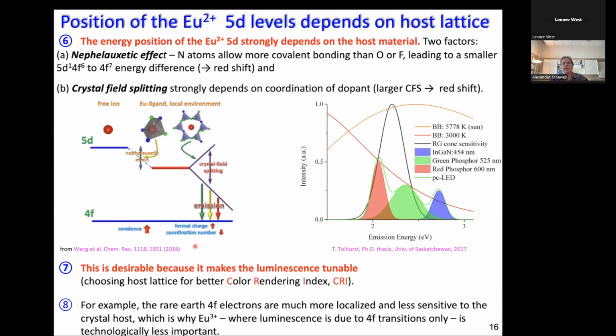Okay, now the whole point about 5D levels is, unlike the 4F, which are very localized, where it basically does not matter in which host matrix you put them, the 4F levels are always in roughly the same energy position. The 5D are very susceptible and sensitive to the host lattice. And this is through two effects. I've shown them here. It matters how strong the bonding is of the nitrogen atoms. This is basically the nephelauxetic effect. And then you see here, this would be the free ion, the 5D 4F. Now, depending on the ligands, you have the first effect. And then, of course, like any orbital that you put into an electric or magnetic field, they are splitting. And it turns out that depending on the crystal field, in other words, depending on the host lattice, you will have different crystal field splitting.